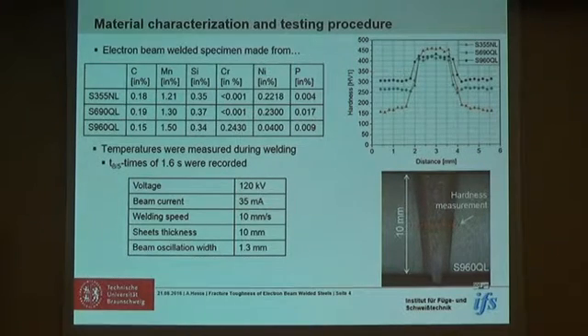After welding, we took cross sections perpendicular to the welds, and we made a hardness measurement on the surface of these cross sections. You can see the results in this figure, and it could be shown that the hardness within the weld seam exceeded 400 Vickers, and in the base material it was dependent on the base material, of course, and we have a relatively high mismatch ratio in the S355 specimen between the hardness in the weld seam and the hardness in the base metal.